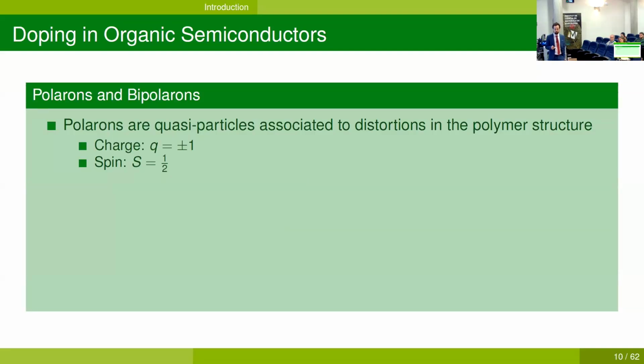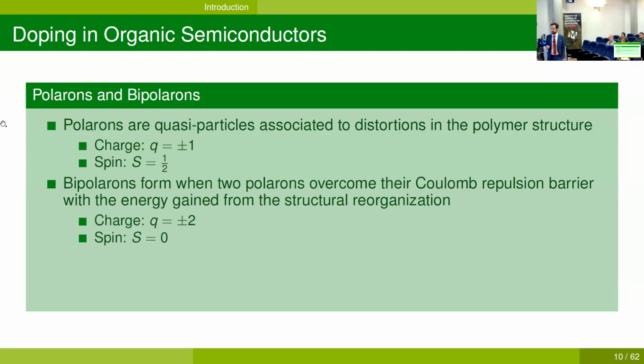When we dope, we are introducing charges in the semiconductors, and these charges are also associated with distortions in the polymer structure called polarons or bipolarons. Polarons have unitary charge and spin 1/2, and bipolarons form when two polarons come together by overcoming their Coulomb repulsion barrier, when the energy gain from the structural reorganization is higher than the Coulomb repulsion, and they have spin 0 and charge plus or minus 2.